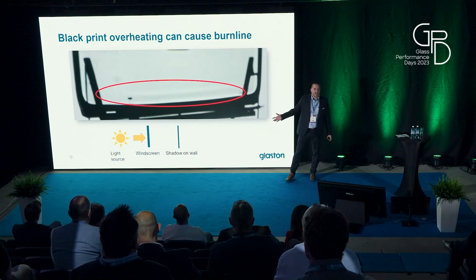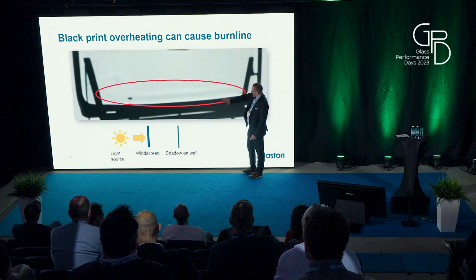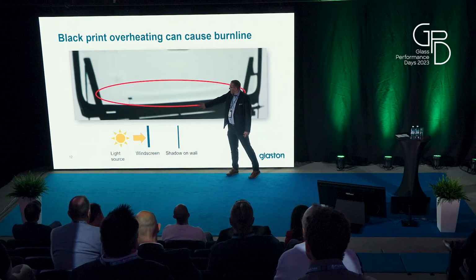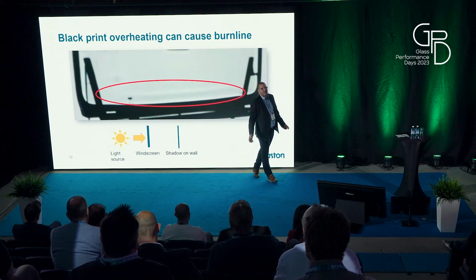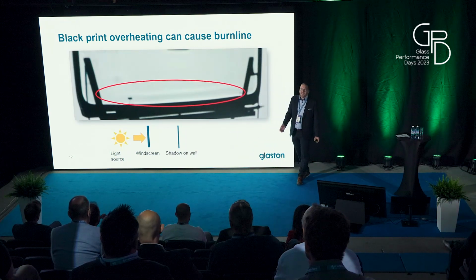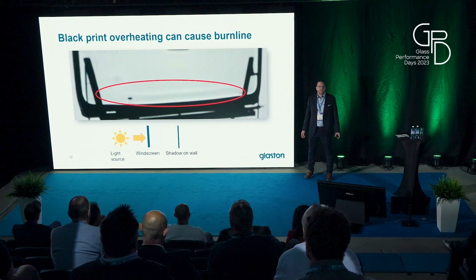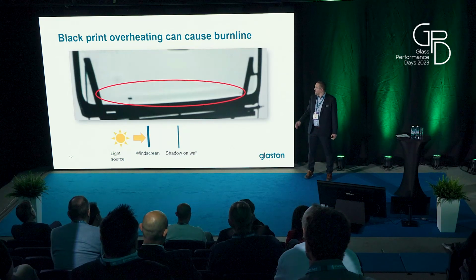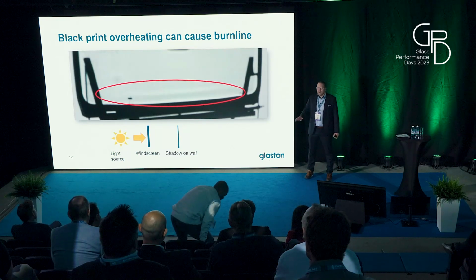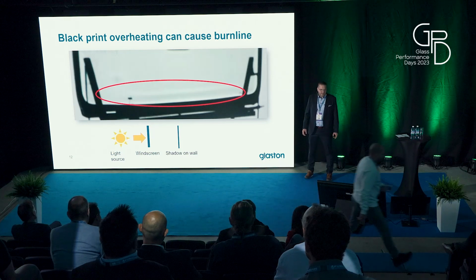And the problem in this one has been that the painted area at the edge and the clear area in the middle are heated at a different speed. And that is causing thermal strains in the glass, which are at the end seen as visual faults. Or if there is a different kind of bending, that's also seen in a similar way.